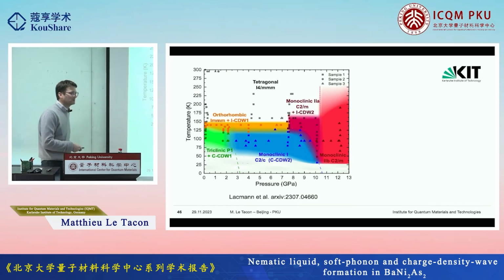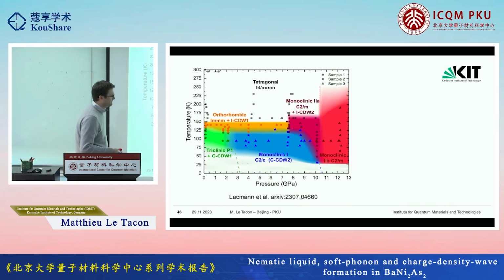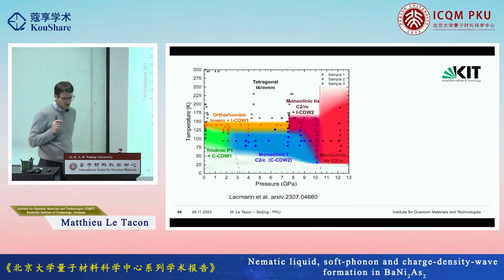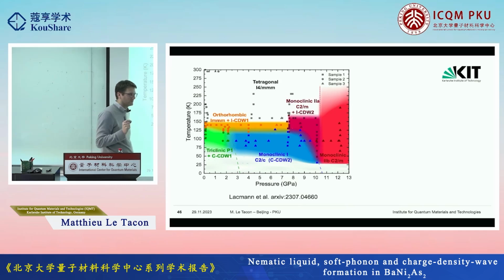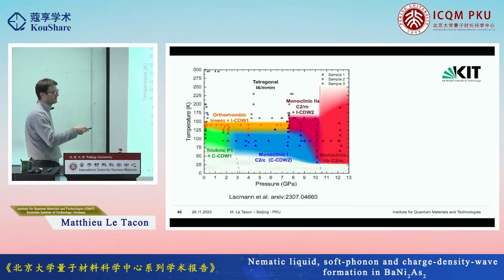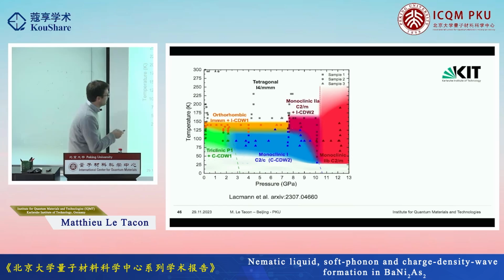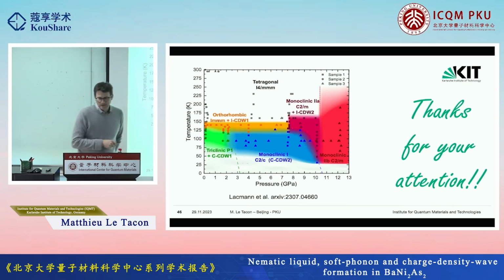I showed at the beginning of the talk many phase diagrams, including charge density wave and superconducting dome. In all of them, you had a decrease of the charge density wave transition temperature as a function of pressure. I know very few examples of a charge density wave transition temperature that increases with pressure. There are a few, but maybe 5% of the total charge density wave systems I know. A system where the incommensurate charge density wave doesn't care about pressure, I've never seen. So there's something very strange here. This charge density wave transition temperature, around 145 Kelvin or something like that, remains pretty stable up to 7 GPa. That really tells us that this kind of phase here is not a normal charge density wave. It's a different beast. I'm just going to stop here, and thank you for your kind attention.